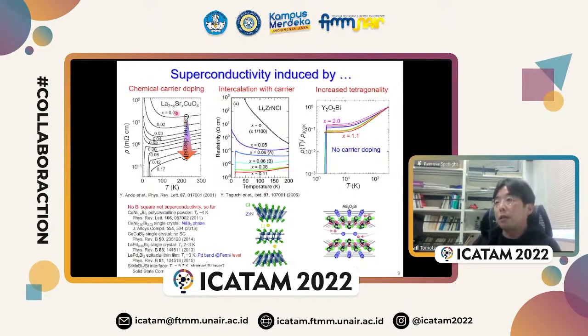For example, this is a perovskite copper oxide. In the case of x equals 0, this is an antiferromagnetic insulator, but with doping strontium, this becomes hole doped, and finally this compound becomes superconducting. And this is a nitride chloride layered compound. In this case, the pristine compound is an insulator, but by intercalating lithium metal, the resistivity decreases and superconductivity appears like this.